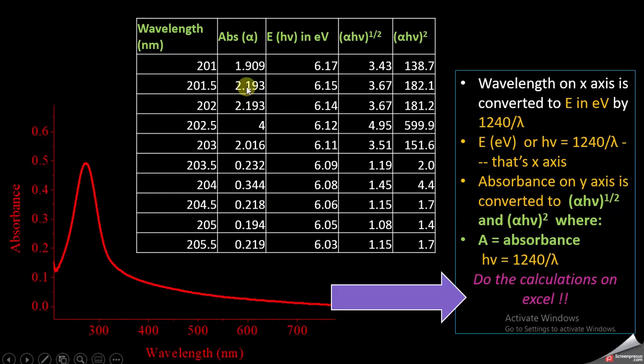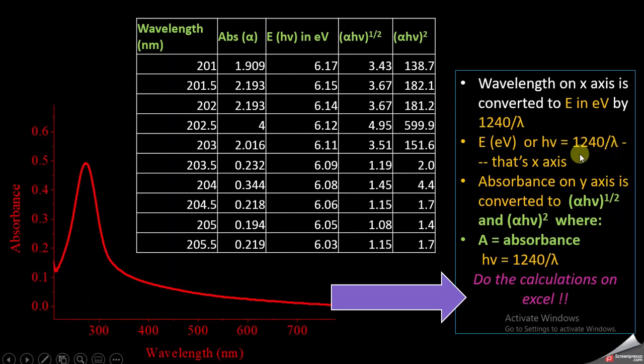The first thing is to convert the wavelength in nanometers into energy hν in electron volts. There is a simple relationship: you divide 1240 by lambda (the wavelength), and in this way your wavelength is converted into energy in electron volts. Here is the data of this wavelength converted into electron volt energy.